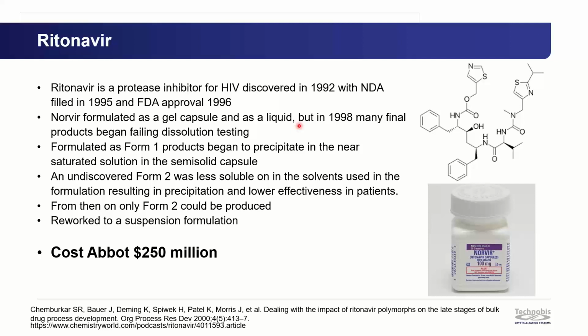But in 1998, many products started to fail their dissolution tests. They had done polymorphism screens and decided that form 1 was what they wanted to take forward. And what they began to find is the capsule began precipitating during storage. And this was an undiscovered form 2, which was less soluble than form 1 in the solvents used for the formulation, and resulted in crystallization and then a lower effectiveness in the patient.